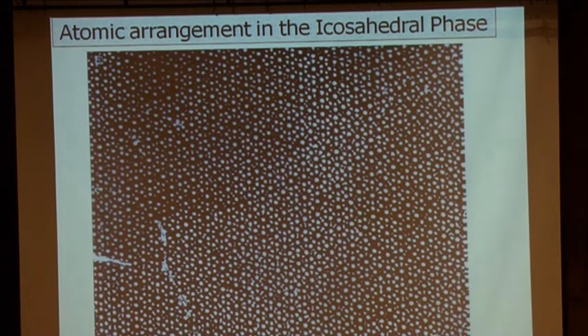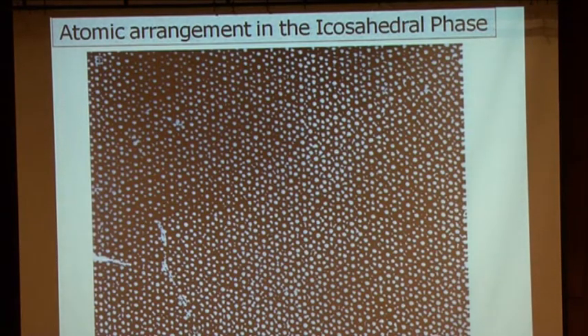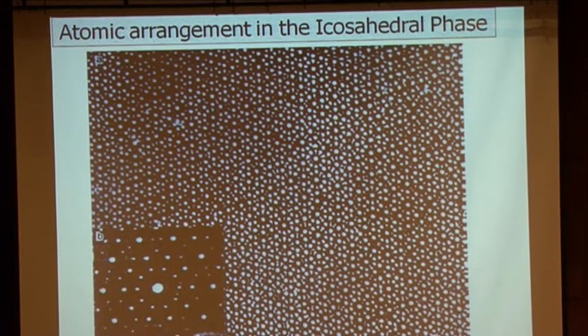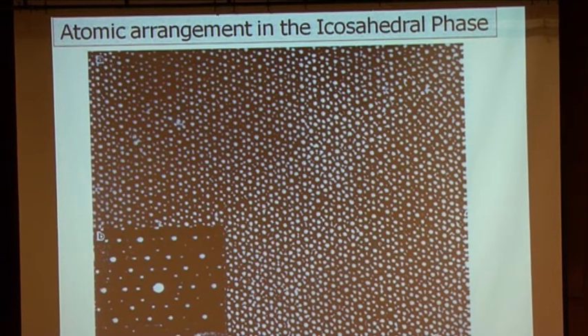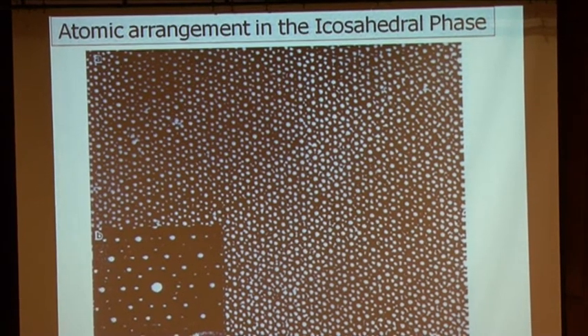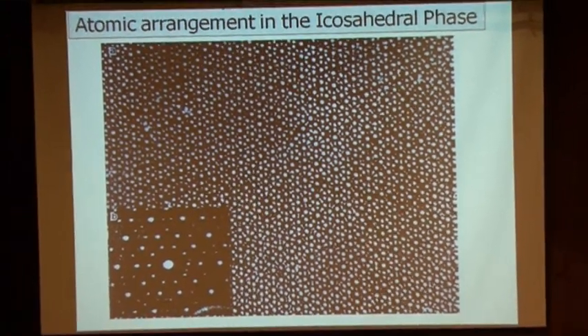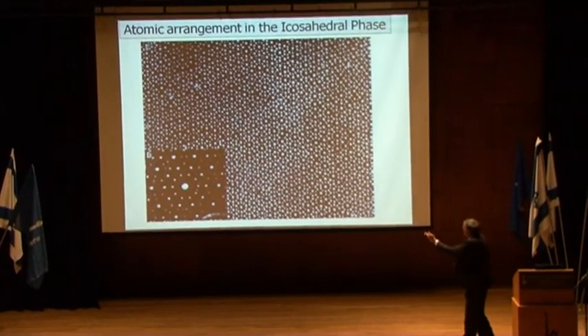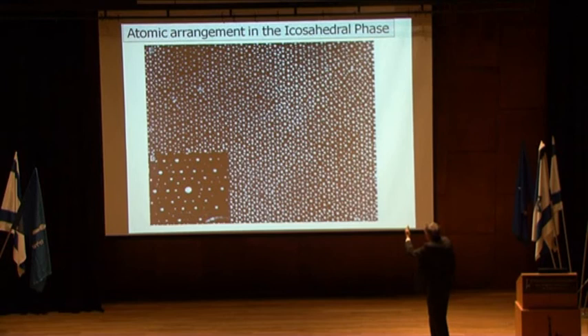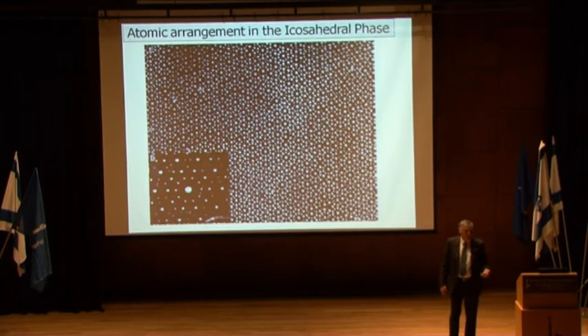And then the last experiment was very, very educating. I did not do that experiment. I did not have, at the time, a high-resolution electron microscope, and my electron microscope did not allow to do that. But friends of mine in France did that experiment, and they sent me the results. And the results are very beautiful. You see, this is the lattice image. Lattice image meaning that you see the atoms in what was called later on the icosahedral phase because of the icosahedral symmetry. We will talk about that. So here is the diffraction pattern, and here is the image. And the image is a Fourier transform of the diffraction pattern, and vice versa.